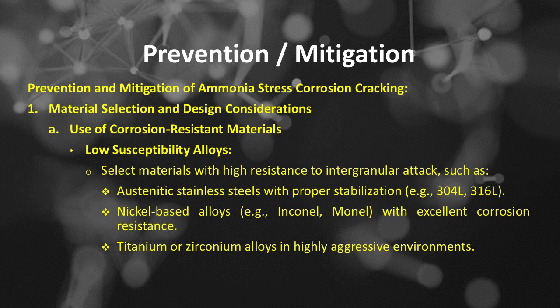Number 1 is material selection and design considerations, includes, number A, use of corrosion-resistant materials, includes, the first is low susceptibility alloys, select materials with high resistance to intergranular attack, such as austenitic stainless steels with proper stabilization, for example 304L, 316L, nickel-based alloys, e.g., Inconel, Monel, with excellent corrosion resistance, titanium or zirconium alloys in highly aggressive environments.